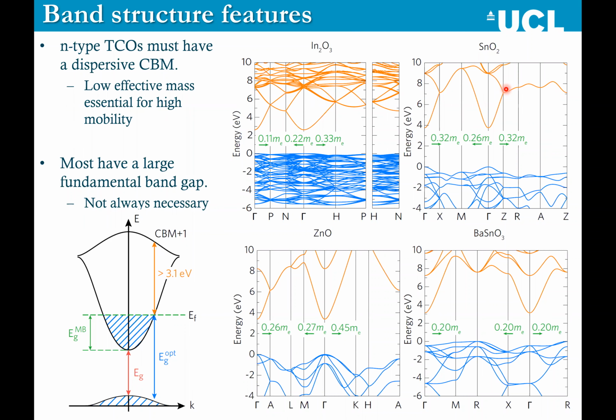They have very low electron effective masses, meaning high mobility. And they also have large separations between the curvy conduction band minimum and the next lowest lying bands in nearly every case. As I said already, most of these materials have these large fundamental band gaps, which means that they are already transparent even before you start doping. But you can dope a small band gap material to make it more transparent. You just always have to be wary of this caveat of the extra 3.1 eV separation needed to the next lowest conduction band minimum.